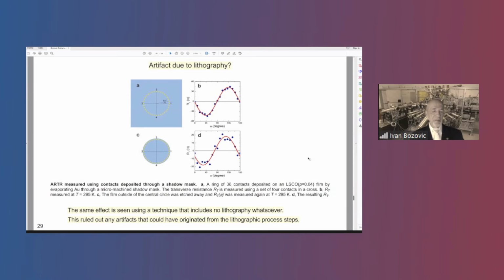Okay, the final suspect on my list is lithography. It is conceivable in principle that some steps in our lithographic process may introduce some asymmetry into devices. And to test and rule this out, we developed a different technique that completely avoids any lithography. Rather, we use a micro-machined shadow mask and deposit gold contacts through the openings in the shadow mask in a circle like this. And then we can use the 2 orthogonal pairs of contacts, like these 2 for the current and these 2 for the voltage. And then we can rotate that in steps of 10 degrees. And this is what you get.